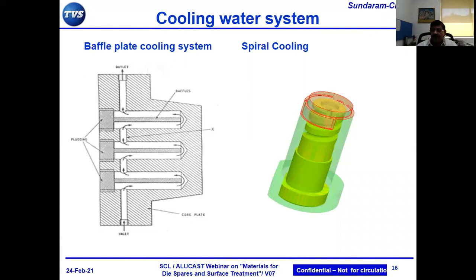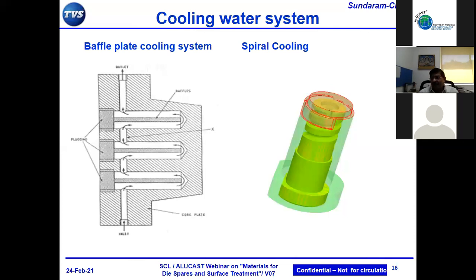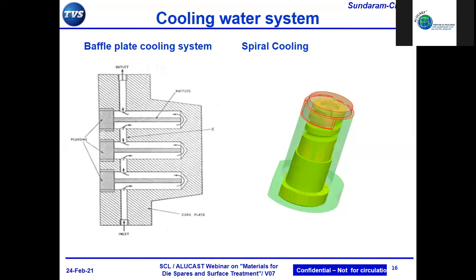where we need to go that extra mile on the interaction of the alloy that is cast and the die casting tool. Because conventionally we have much higher iron content in the aluminum alloy, which actually enables the pressure die casting process to be easy without any sticking of the metal to the die, and easy ejection. And soldering is something which can be avoided with higher iron in the liquid metal. So because of the requirements of the application for higher ductility, alloys with low iron content are required for die casting. So this becomes a challenge.